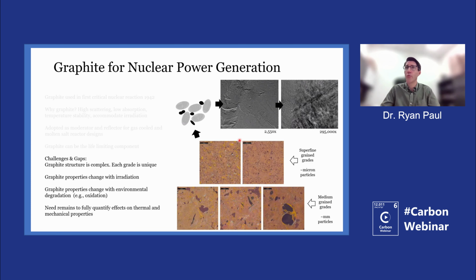But I think the important thing to stress, as many of you probably know, is that there is really no standard graphite grade. There's no standard manufactured graphite grade. Each manufacturer makes a slightly different material, depending on the raw materials and their process. And so that's one issue already, the diversity of different graphite microstructures that can be formed, representing the different grades. And then, of course, the changes over time. Graphite properties change with irradiation. They change with potential environmental degradation like oxidation. And so there is an ongoing and very urgent need to better quantify this.